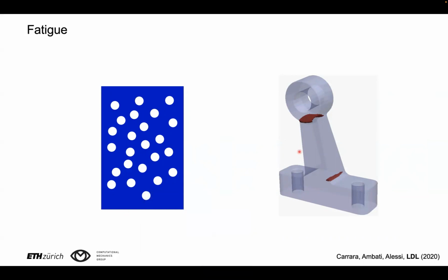But anyway, we have been able to extend the phase field framework to fatigue and recover the Paris law as a consequence of the phase field model, rather than having to input the Paris law from the outset. So if you could see this video on the left, you would see complex cracks due to fatigue propagating all over the place in this specimen.